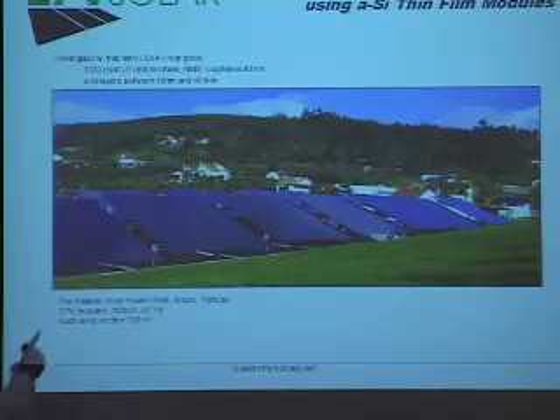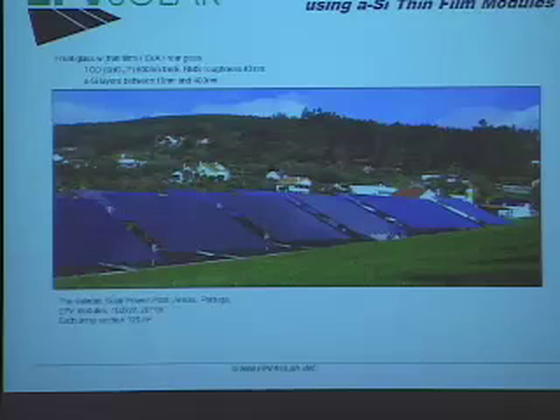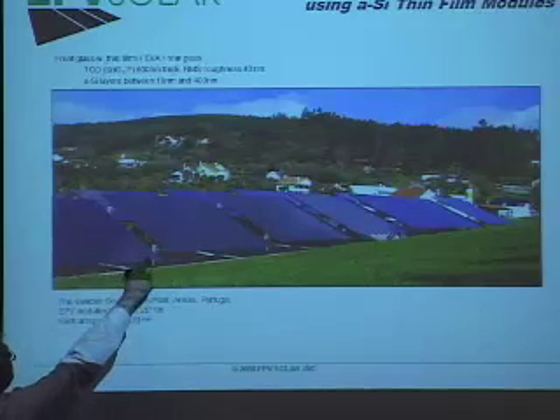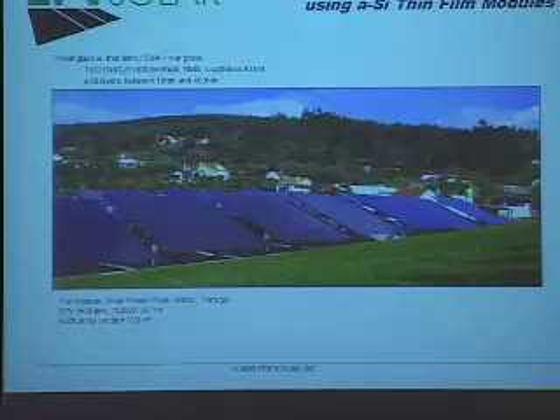Each of these array sections, these big blue squares, has an area of 120 square meters, and you can see they're composed of solar modules, each about 0.8 square meters in size. So this represents the scale of what we're doing. You can see some of the numbers, the film thicknesses, and so on. Some of the layers are 10 nanometers in thickness, maybe 50 angstrom, 50 atom diameters, if you like, and roughnesses of 40 nanometers. So we are controlling properties on that scale, but then we go out and we coat acres of land with modules.